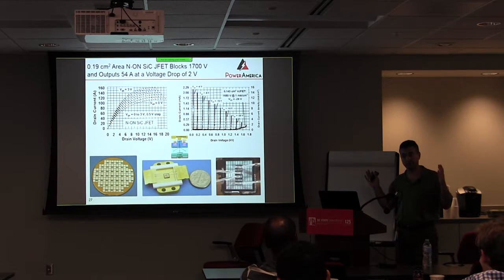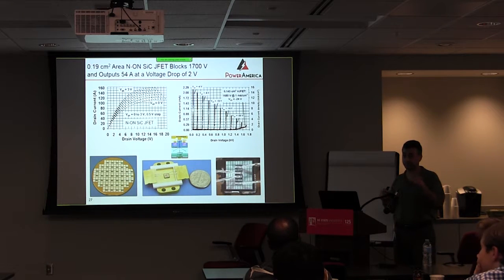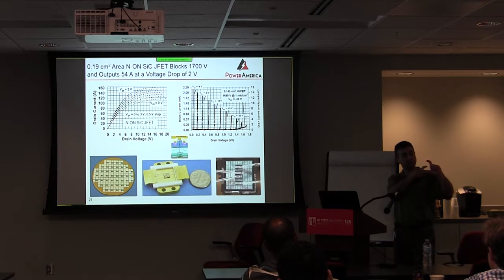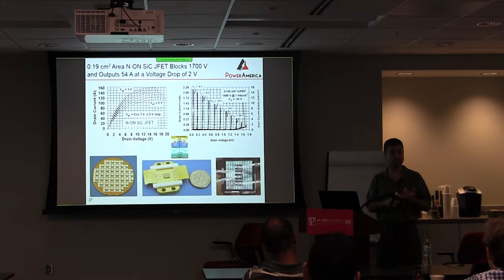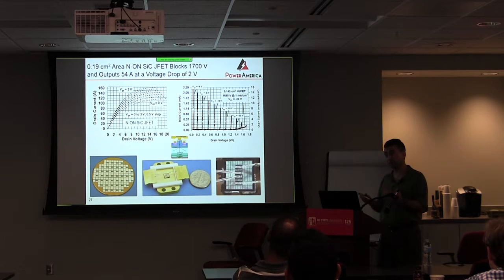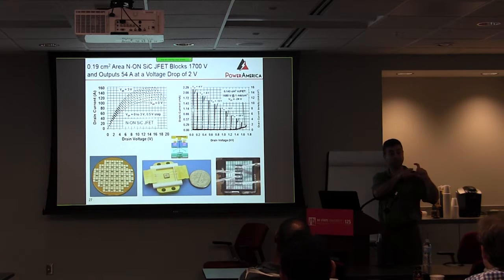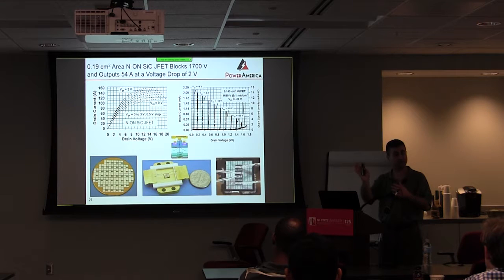Now, if you look at silicon carbide or GaN or any other new material, right, you're going to make wafers, they're going to have defects, right? Because it's a new type of material. And any device you put on the wafer with a defect inside, it will either fail right away, or depending on the defect, it will compromise its reliability and performance. There are certain defects in silicon carbide on the wafer that if you make a device and one of those defects is there, the device will fail outright. And then there are other defects where they make the breakdown voltage softer, and then as you keep stressing the device, as you keep biasing the device, it gets worse, worse, and worse, and then it fails. So it's a reliability issue.